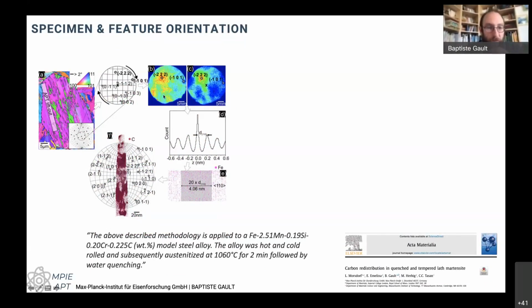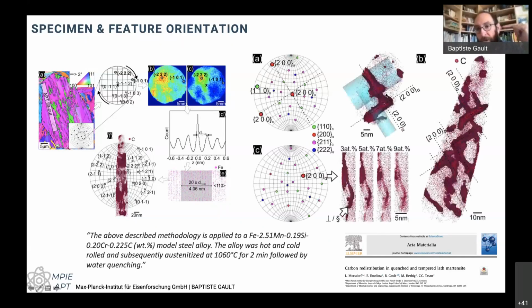And then we can start to look at whether we find these atomic planes inside of the reconstruction, and we do. Then we can use this information to identify on which planes some of these very early stages of the carbides that are forming are sitting. And we can see that they are located at 90 degrees from each other. We can determine that with respect to the main orientation of the needle, they're actually sitting on the 100 planes or 200 planes. So this can also be very interesting and important information when we want to identify some of the phases that we detect, especially when some of these phases are very early stage metastable phases that have not necessarily been documented before.